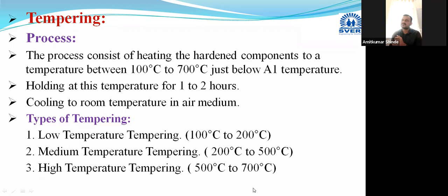These are some important terms. The remaining amount will be tempered martensite. Some amount of tempered martensite will be there in high temperature tempering, consisting of ferrite plus cementite, and the cementite is globular or spherical in nature. Hence, more toughness will be obtained in high temperature tempering by eliminating the internal stresses in the component caused by the hardening.